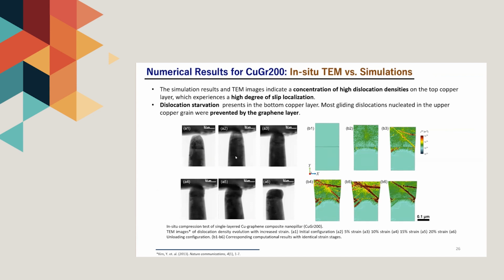The deformed configurations of the simulations show strong slip bands and traces of plastic deformation on the top layer of copper graphene composites, which are matched with the distribution of dislocation density and deformation measurements in the TEM images, and you can see them here.